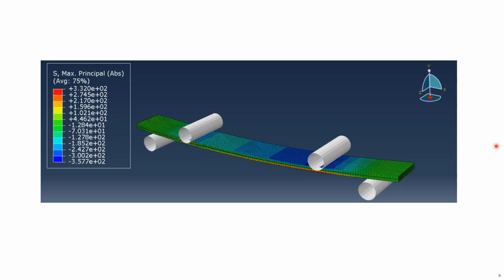So this is a virtual crack closure technique for delamination. We will show the input files. As you can see, I modeled it here as a continuum shell, but the stresses in the upper and lower plates are not in my scope. What I'm looking at is the delamination strength. Because of that, I used effective material properties, and it lowers the computational time significantly, I would say, when you compare. Okay, yeah, we can go on.